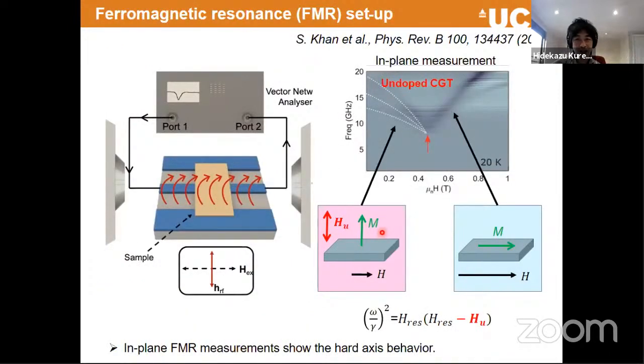Now, just moving on to the FMR experiment, I probably should speed up. I believe that many of you know the FMR experiment already, so I just skipped the basics. But this is a typical result when we measure the CGT undoped, and when we apply the magnetic field in plane. And this is a bulk result.